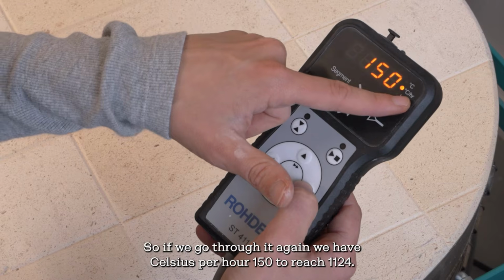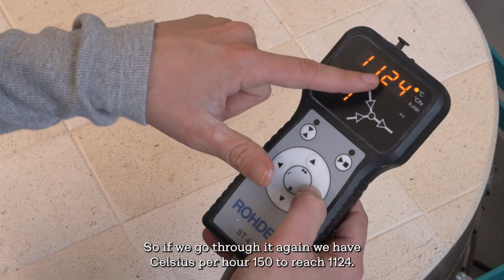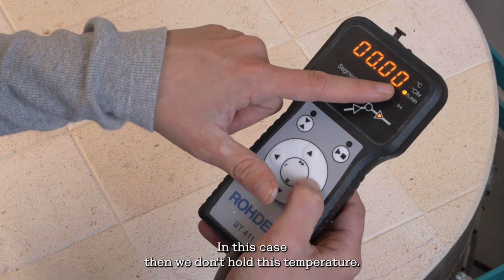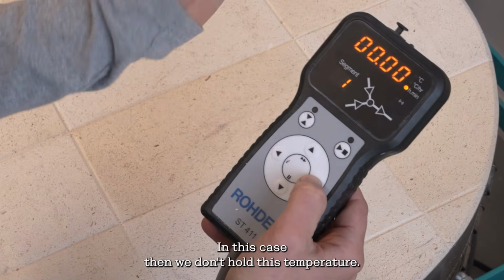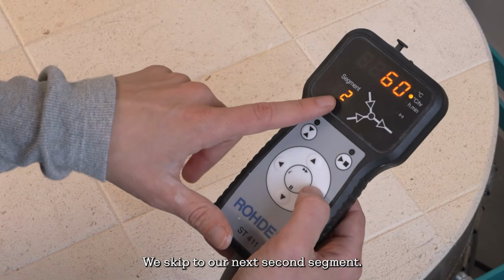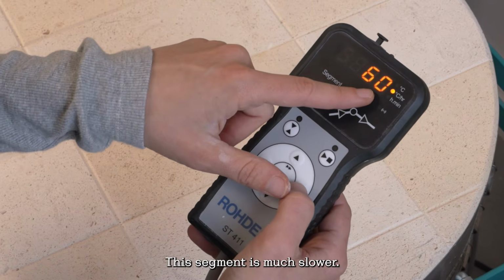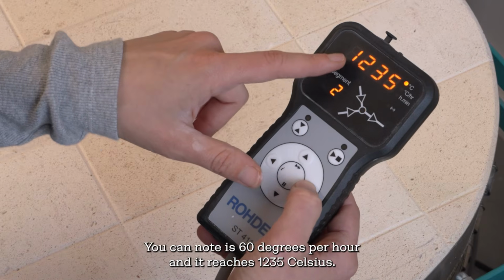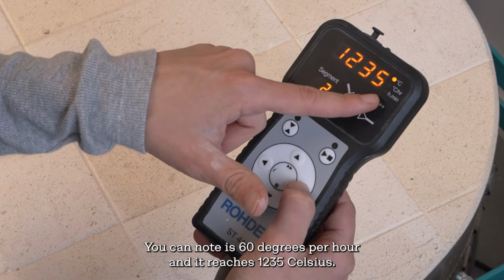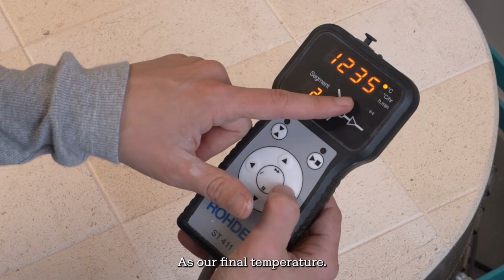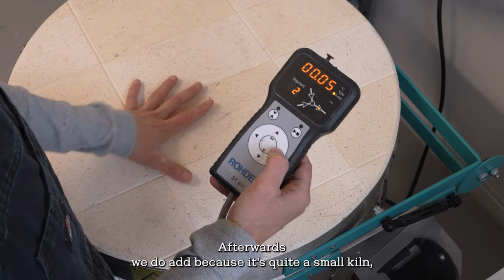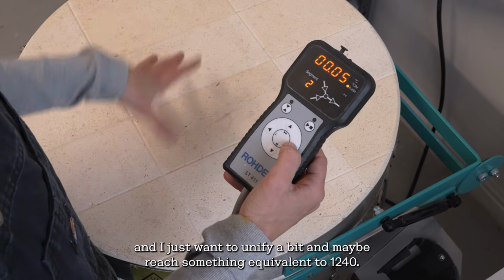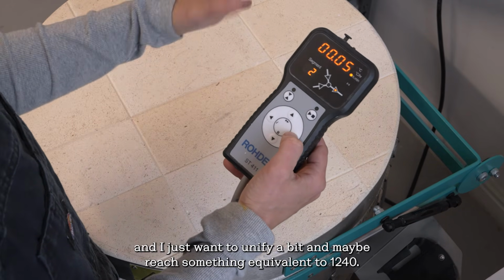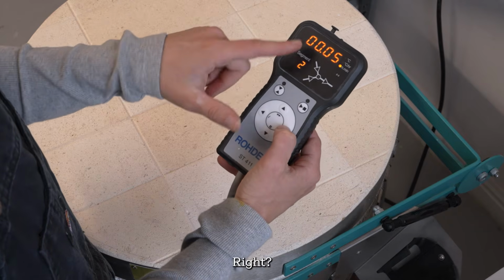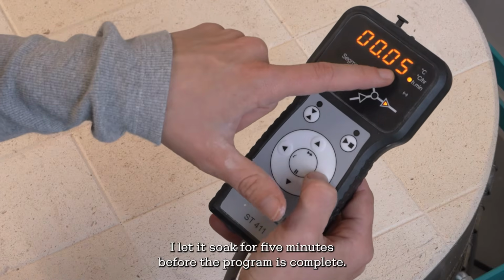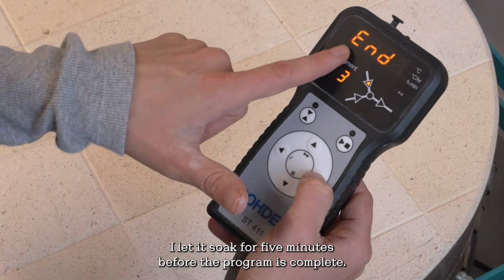So if we go through it again, we have Celsius per hour, 150 to reach 1124 in this case. Then we don't hold this temperature, we skip to our second segment. This segment is much slower, you can note, it is 60 degrees per hour, and it reaches 1235 Celsius as our final temperature. Afterwards, we do add, because it's quite a small kiln and I just want to unify it a bit and maybe reach something equivalent to 1240, right? I let it soak for 5 minutes before the program is complete.